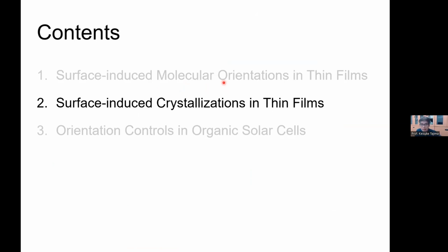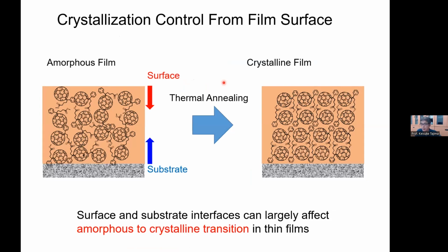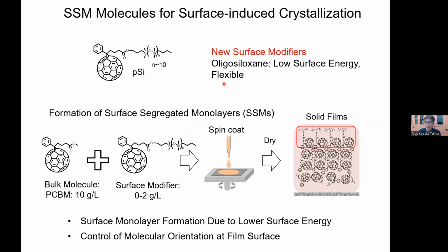Okay, so the second part is related, but it's another challenge: to control the crystal structure in the film from the surface. You know that when a molecule crystallizes, it's highly dependent on the shape of the molecule. But of course, when you crystallize the material in the film, the surface or substrate interface affects crystallization a lot, like epitaxial growth of the crystal. And when you thermally anneal, it crystallizes, but these affect the structure and the crystallinity of the material. We wonder if this surface-segregated monolayer can affect this crystallization process in the film, and we want to control it to get preferable material properties in thin films.